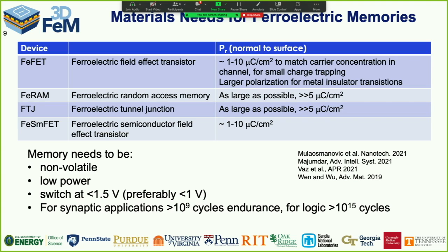In fact, it's problematic. In contrast, if I go for a ferroelectric random access memory, now I get the most signal margin if I have the biggest possible polarization. And honestly, below about 5 microcoulombs per centimeter square, I can't detect the difference between 1 and 0 anymore. So I'd really like to be well beyond 20 microcoulombs per centimeter square. Ferroelectric tunnel junctions, people are still kind of figuring out how that works. We actually change the propensity for tunneling through extraordinarily thin ferroelectrics based on the interaction between the polarization and the contact materials. There again, I'm going to need a giant polarization.